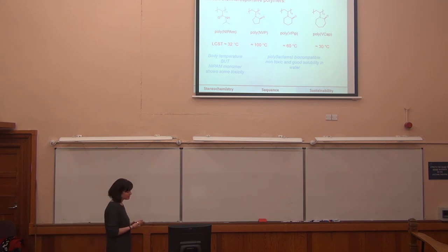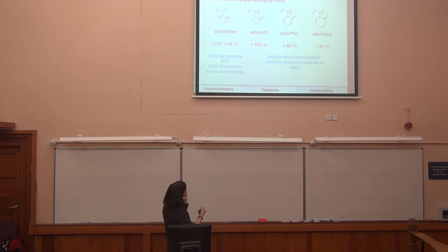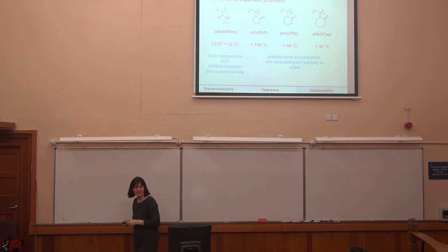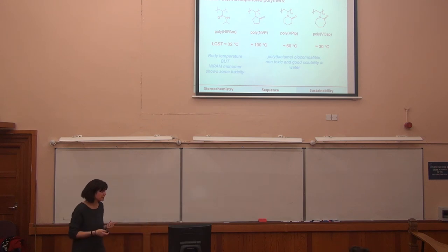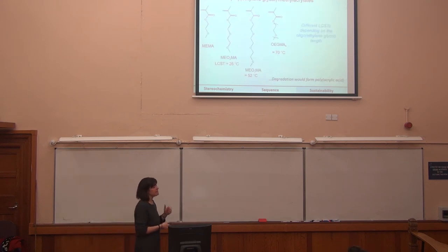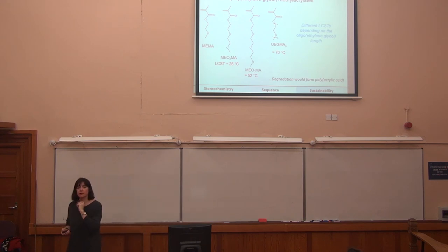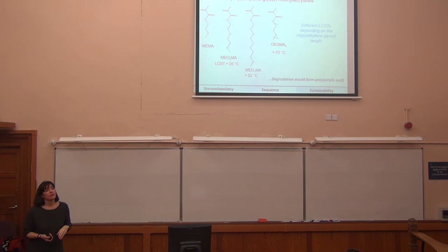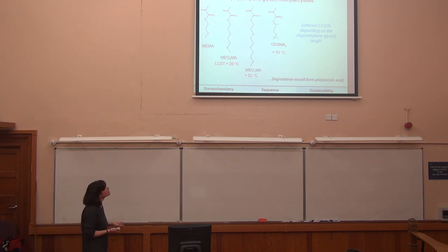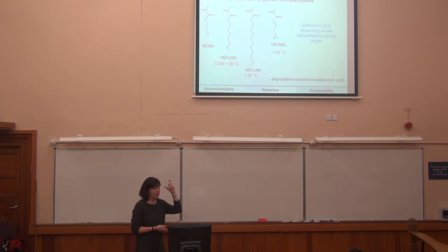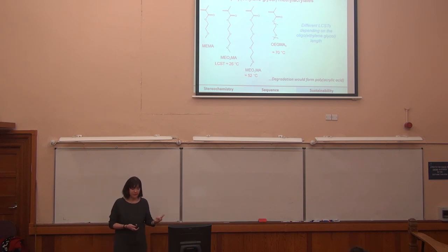The difficulty is these are all the commonly used ones. This is the most commonly used one, but the monomer has toxicity. These aren't bad, but they're really hard to make and scale, and some of their degradation products are pretty nasty. This is a really interesting family of polymers that was introduced. The problem is when they degrade, they form polyacrylic acid, which is really quite nasty. So we were interested in making mimics of this, thinking about what the products upon degradation would be of some of the materials.